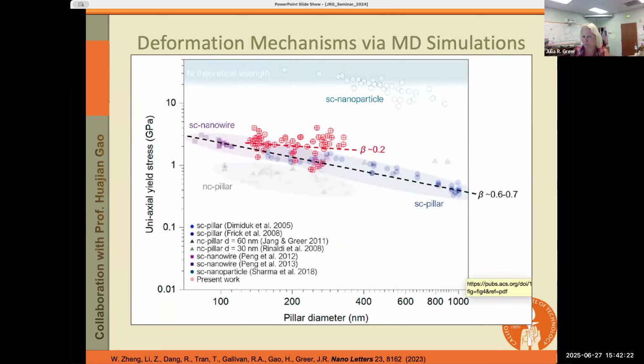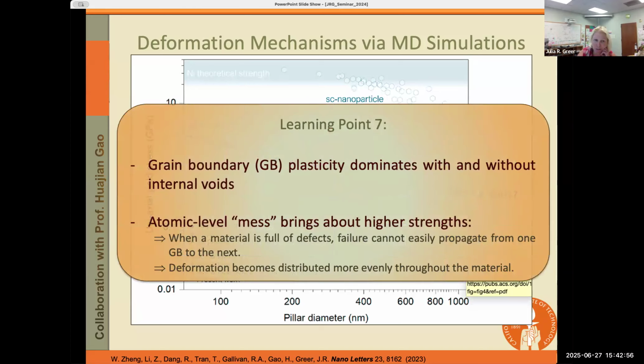And I'd like to take a little bit of a pause here because there have been people working for 2 decades now, actually, since 2005 or so, in this field. And this was kind of everybody's understanding: that nano-sized metals always exhibit the smaller, stronger size effect if they're single crystals, or smaller, weaker size effect if they're nanocrystalline. So what we're learning here is that you can actually fully suppress the size effect by the right composition of nanocrystallinity and pore distribution. So the size effect is something that not only can be tuned, but can also be suppressed. So this was an interesting observation for us.